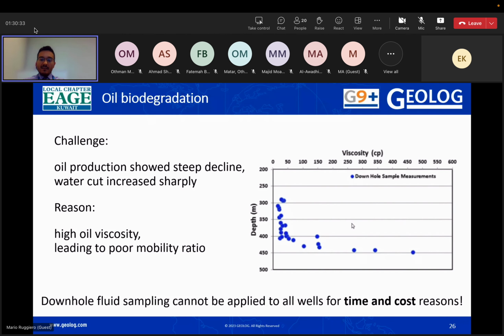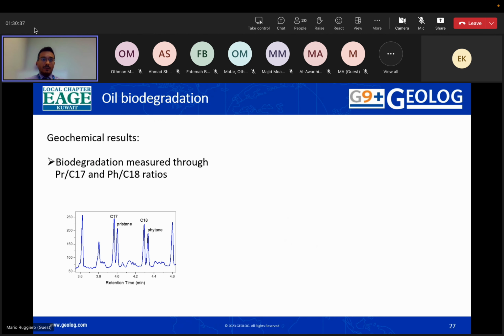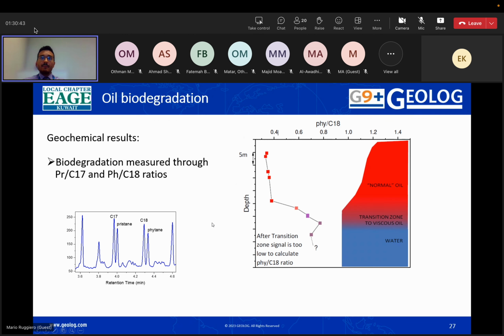So we can apply this very simple measurement at the field using, again, the same markers. In particular, in this case, we will use phytane over C18. And we see that when we get close to the transition zone, this ratio highly increases, showing biodegradation. Of course, biodegradation occurs because close to the oil-water contact, you start having bacteria, so your viscosity increases, and your production decreases.